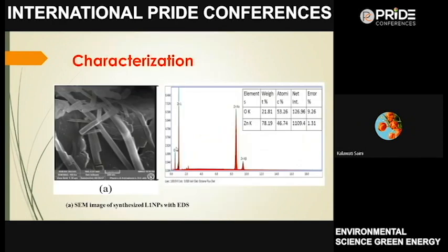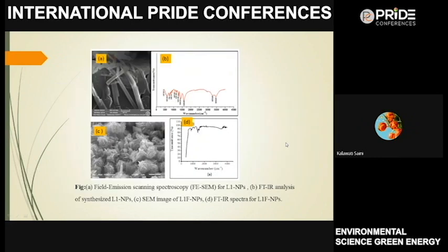And these are the FESEM and EDX regarding L1 nanoparticle, means 1 ml extract when used in synthesis of zinc oxide particle. Herein again shows the purity of synthesized nanoparticles. These are the percentage ratio regarding oxygen and zinc. No other element is found. And these are the FESEM images of zinc oxide when it is synthesized with leaf extract of banyan tree. When 1 ml extract is used, there is 10% extract taken. And these are the FTIR spectra.